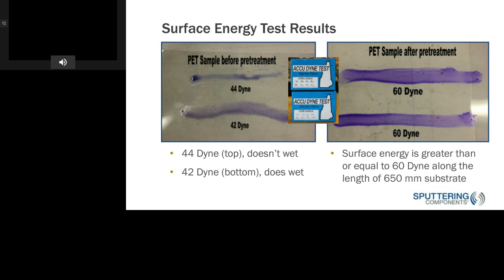The top was at 44 dynes and didn't wet, and then the bottom was at 42 dynes that does wet. And then there's a picture on the right, the PET sample after pre-treatment, where you can see the limit of the test pen was actually 60 dynes, so we know that we achieved at least 60 dynes or more, and that was along the length of a 650 millimeter substrate.